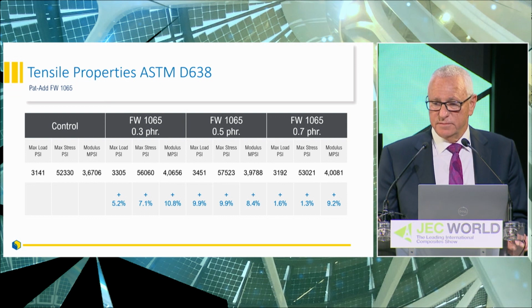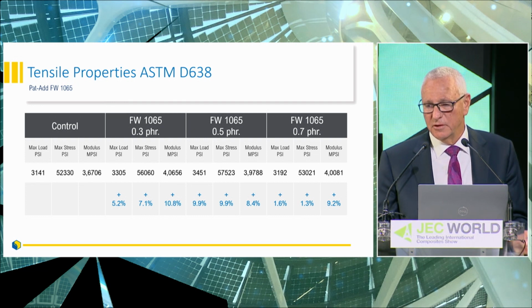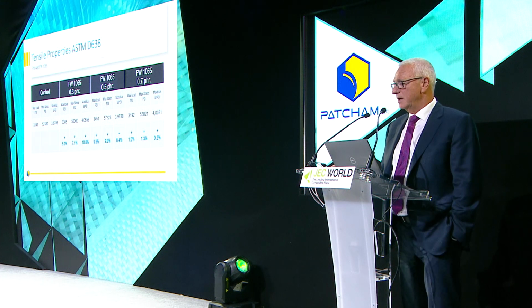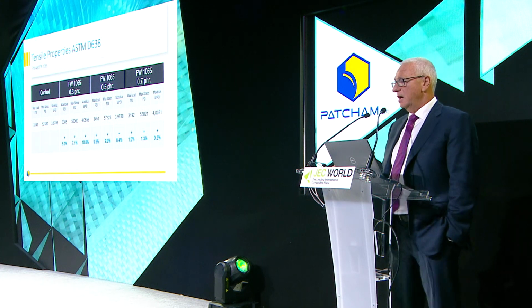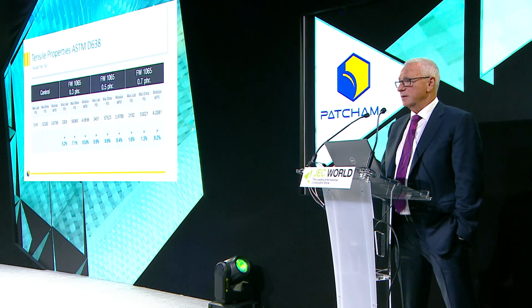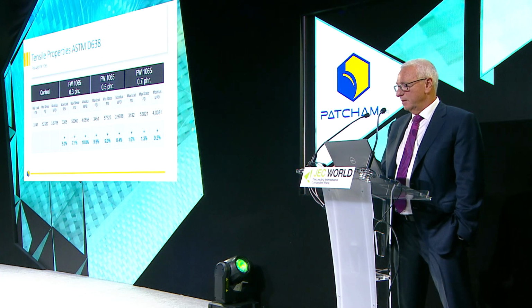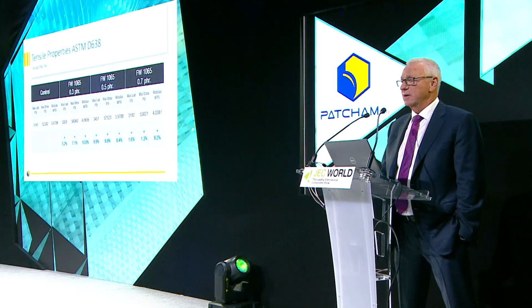So on the tensiles, on the pultrusion, the results weren't quite as dramatic as we saw on the hand-laid laminates, but it's still significant in that you got maximum load in the 0.5. I draw your attention to the 0.5. It seems to be the sweet spot. We got almost a 10% increase in maximum load and maximum tensile strength. Slightly less on the modulus.